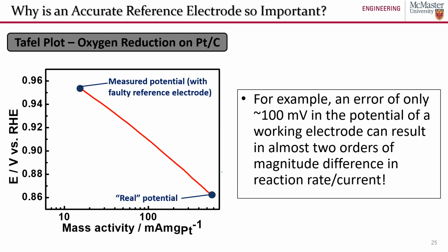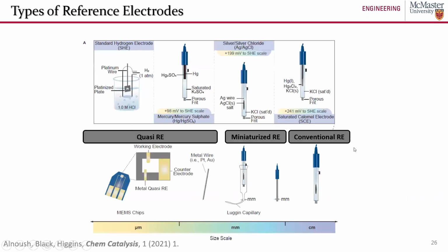So at about 0.95 volts versus RHE, platinum would generally have a mass activity of about 10, maybe 20 milliamps per milligram. If we have an electrode potential of 0.85 volts versus the RHE, we're going to be up on the order of 200 milliamps per milligram of platinum. So huge differences that could be convoluted if you have a reference electrode that's about 100 millivolts off, or even 50 millivolts off. Imagine the worst case scenario if you have a reference electrode that is several hundred millivolts off. This can provide a lot of issues with your results and with your interpretation of those results. And so it's best to take these into account before you run your experiments and make sure that you're carefully selecting, using, and validating your reference electrodes.